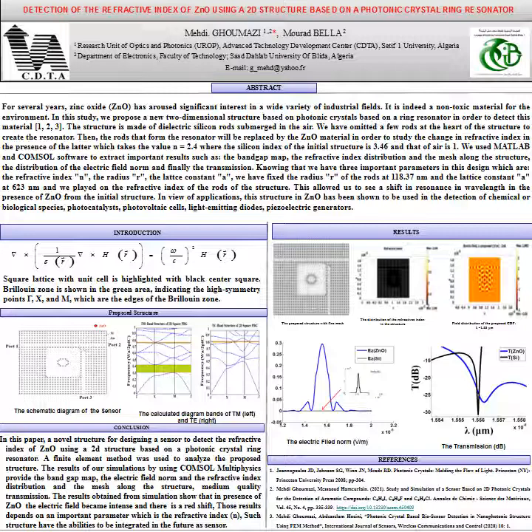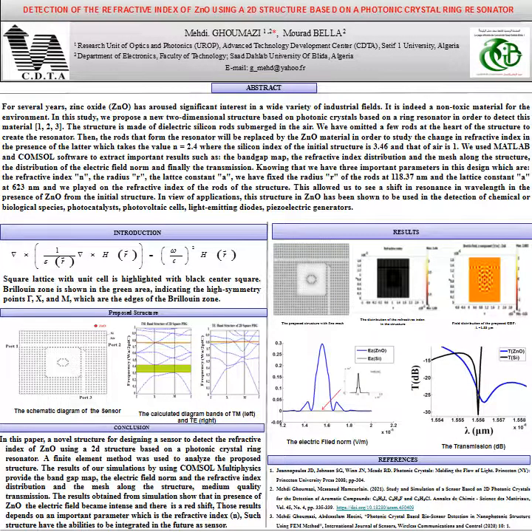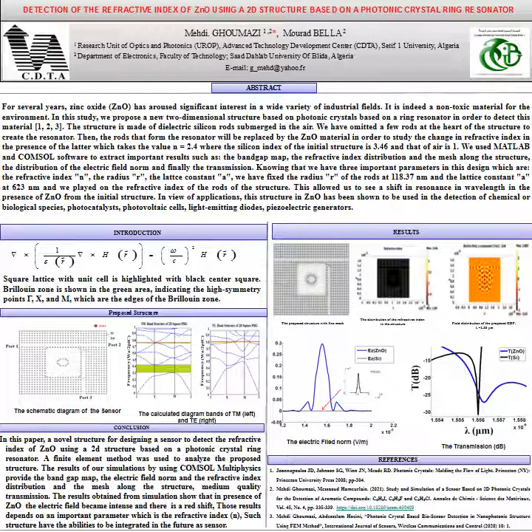the rods that form the resonator will be replaced by the ZnO material, in order to study the change in refractive index in the presence of the latter, which takes the value of n equal to 2.4, where the silicon index of the initial structure is 3.46 and that of the air is 1.